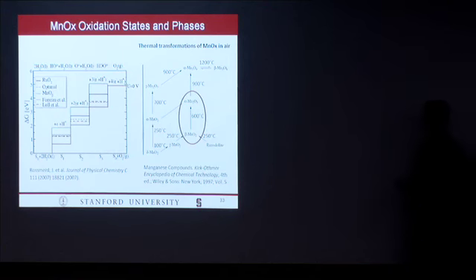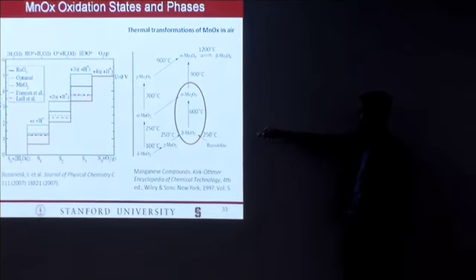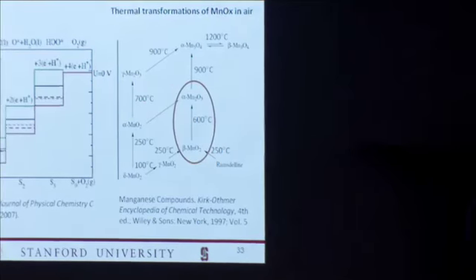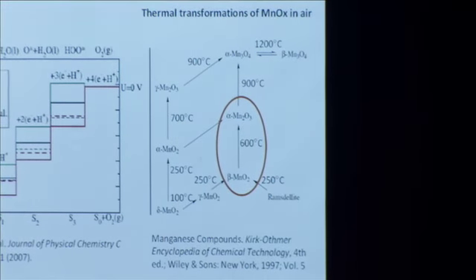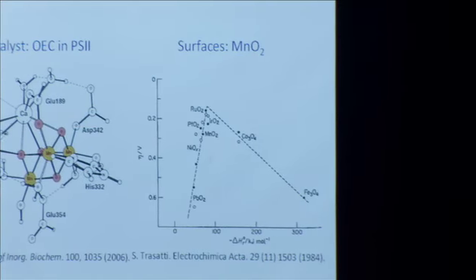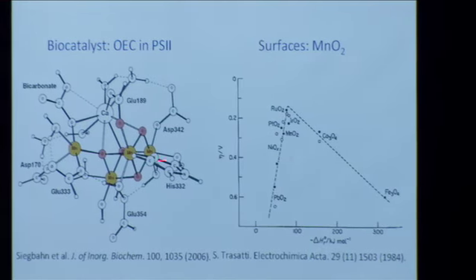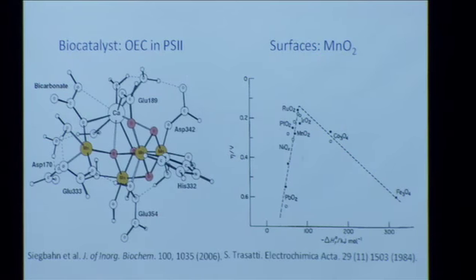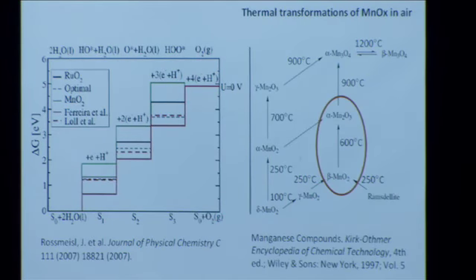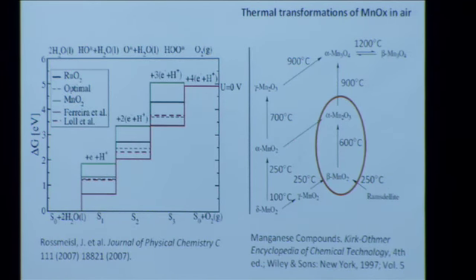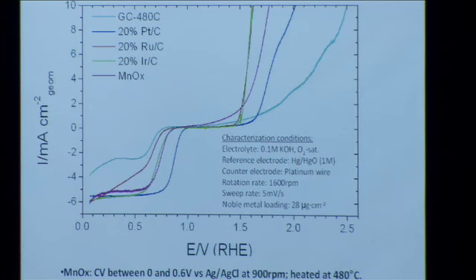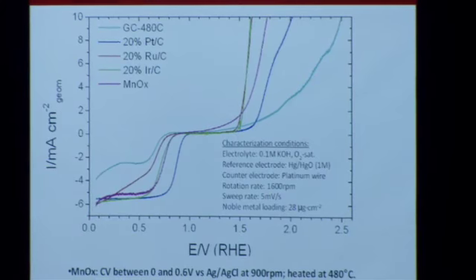So our question is, well, again, this is MnO2. What about exploring phase space that's outside of MnO2? And our hypothesis is, if we go back one slide and just take a look at the Oxygen Evolution Center, during operation, these manganese are either in a 3+ or 4+ oxidation state. So this is what inspired us to try to study these particular materials, really mixed phases of Mn2O3 and MnO2. And so we've really explored that phase space quite a bit. I'm going to show you our best result for our manganese oxide.